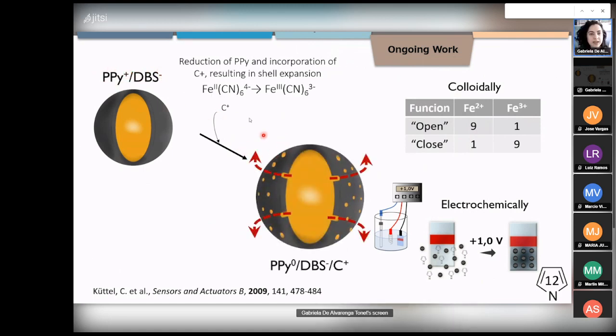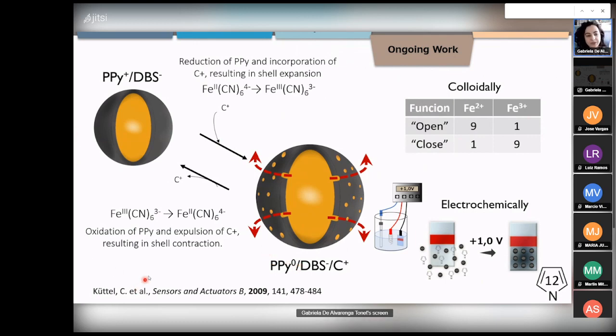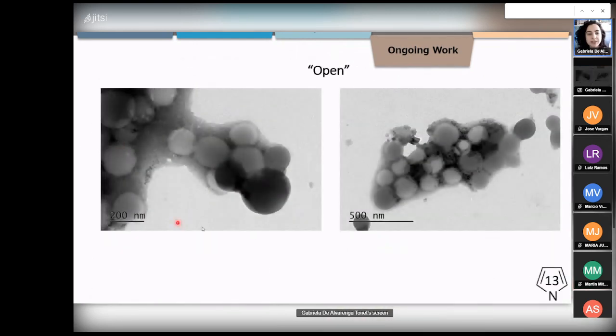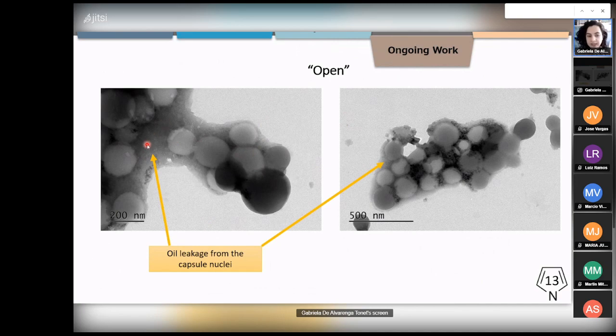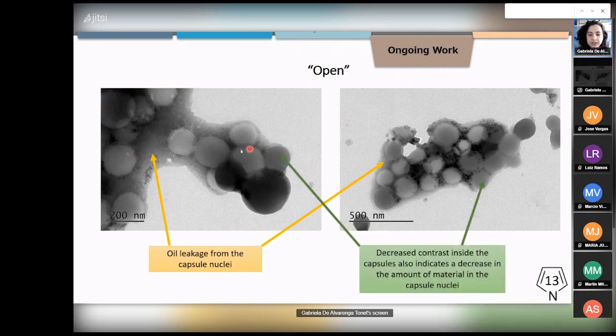And when we reduce this and incorporate a cation, we have the expansion of the shell and release of, in this case, the linseed oil. This process should be reversible once we oxidize the capsule again. So far, we see that when we subject the capsules to an open solution, which is the solution that reduces the shell, we can see the oil leakage from the capsule nuclei in the TEM images, and also a decreasing contrast on the area that should be the capsule, which indicates that the material is leaving the capsule nuclei and actually being released in the media.